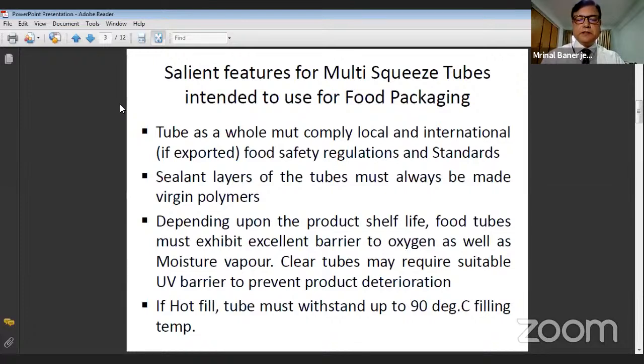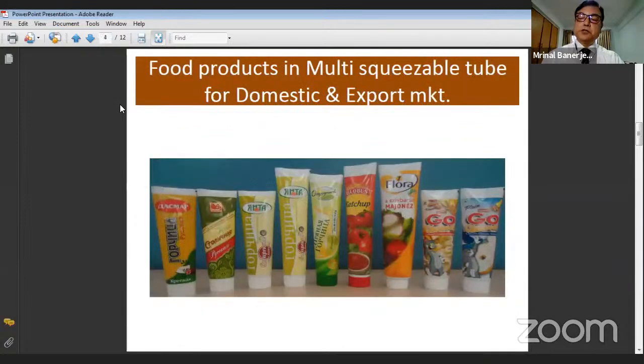Sometimes if it is a clear tube and you want to pack any curry paste or chili, ginger, garlic paste, we have seen that without any UV barrier or UV block, the product gets rancid. It turns from white to a little yellow and dark yellow over time. And that happens with diffuse light also, not necessarily direct sunlight. So that's why some tubes we have designed, I'll come to in the next slides, we have produced with the UV cut.